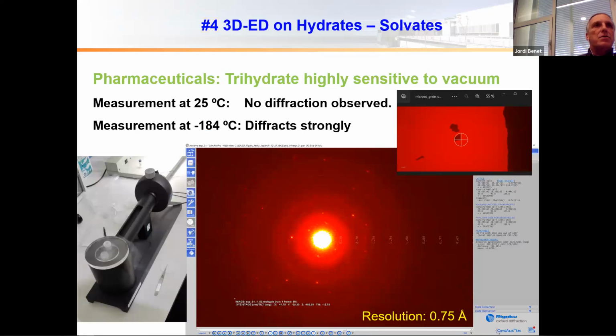And so first we started with a room temperature measurement, and we didn't see any diffraction. So the crystals were destroyed by the vacuum and at room temperature. But if we started to measure and cryopreparated it at minus 184 degrees Celsius, or at around 100 Kelvin or 90 Kelvin, we could see really nice diffraction up to resolutions of 0.75 angstroms.